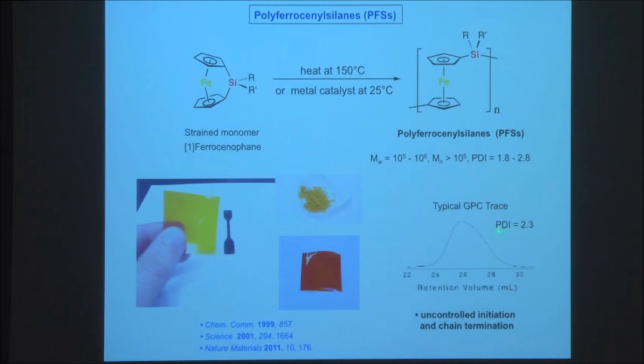And you can characterize this by the polydispersity index, or PDI. If all the chains were the same length, the value would be 1. And as you can see, it's a broad distribution here, and the value is 2.3.